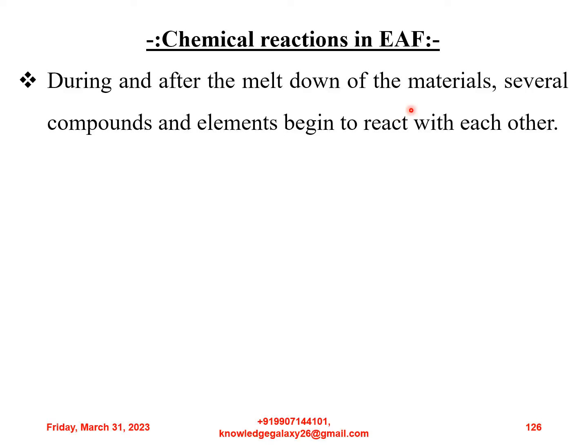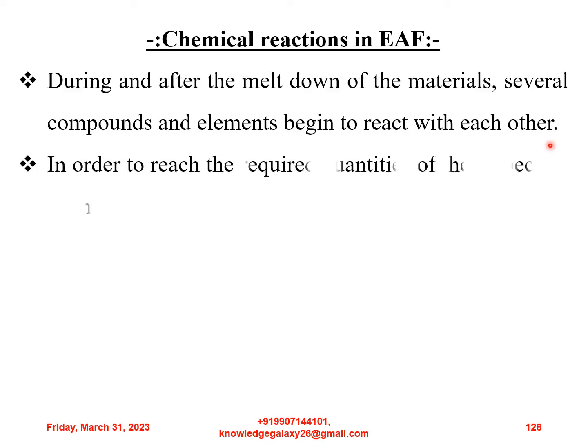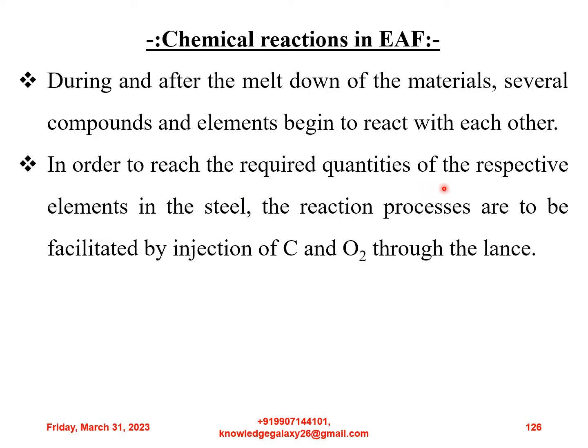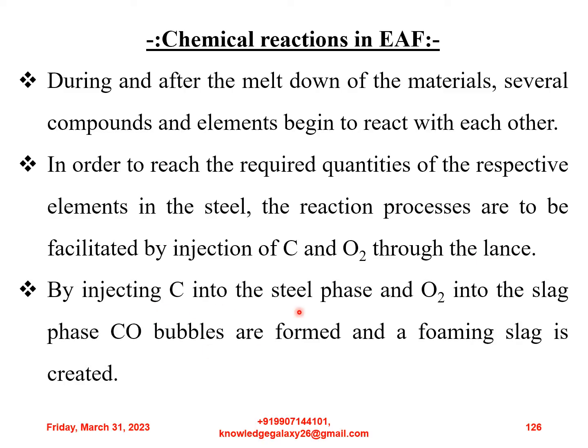So now let us discuss the chemical reactions in the electric arc furnaces, steel making technology. During and after the meltdown of the raw materials, several compounds and elements begin to react with each other. In order to reach the required quantities of the respective elements in the steel, the reaction processes are to be facilitated by injection of carbon and oxygen through the lances. By injecting carbon into the steel phase and oxygen into the slag phase, CO bubbles are formed and a foaming slag is created.